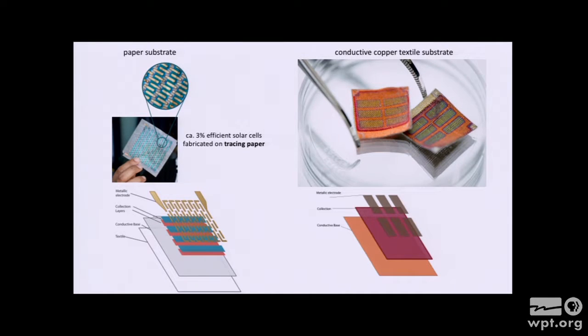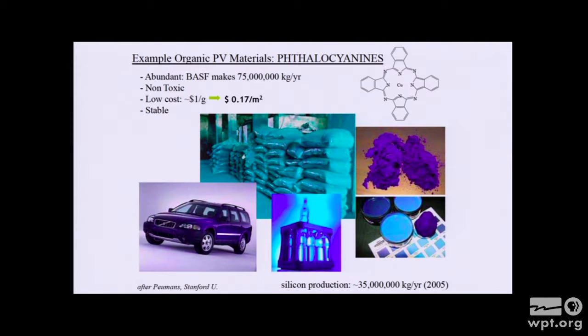So silicon is very, very sensitive to even micro cracks in the system. So even if we have a conductive fabric substrate, if I grow silicon on it, first of all, silicon's grown at about 400 degrees, so my fabric is going to burn. But if I somehow got around that chemically, even if I grew silicon crystals from the ground up, if I bent it more than 10 degrees, it's going to become unusable again, okay? So even to think about our photoactive layers, and partly this is my own bias, I like organic materials, that's what my lab focuses on, we use organic dyes as our photo collection layers.